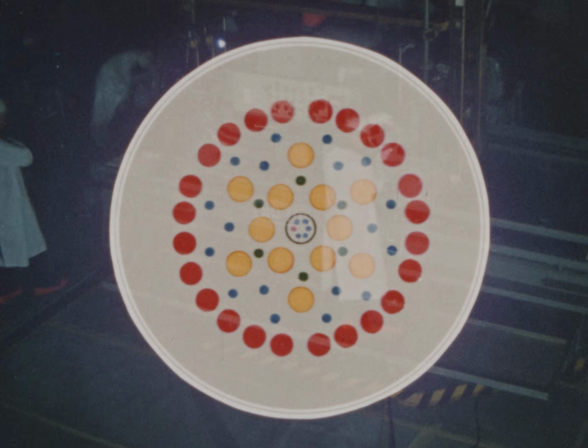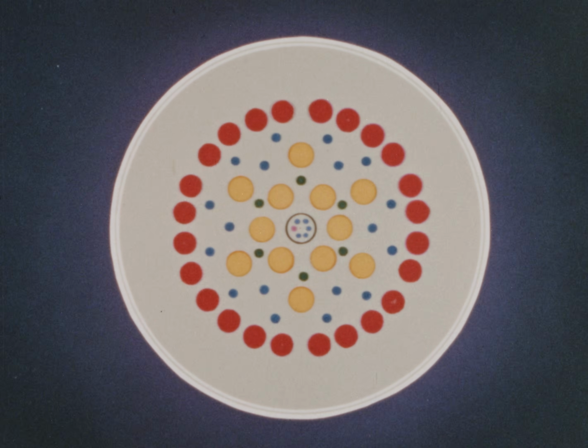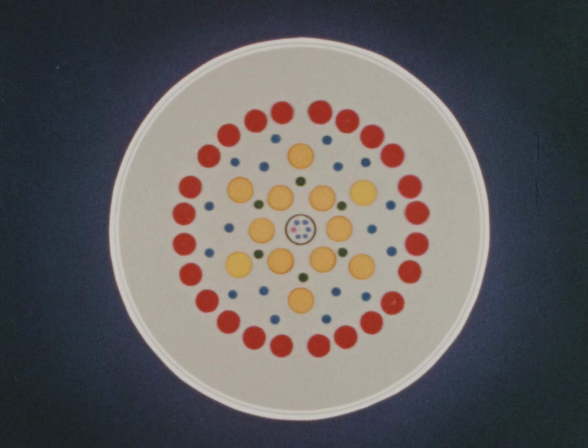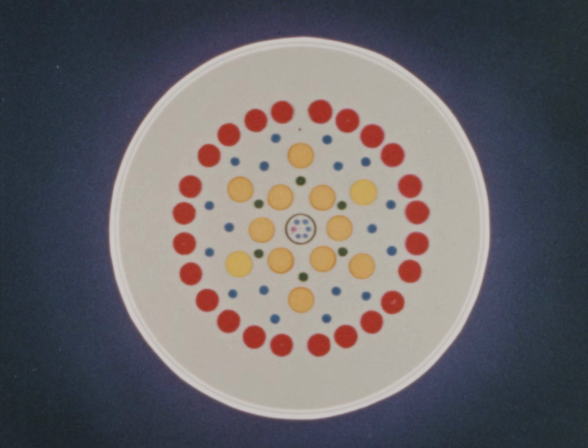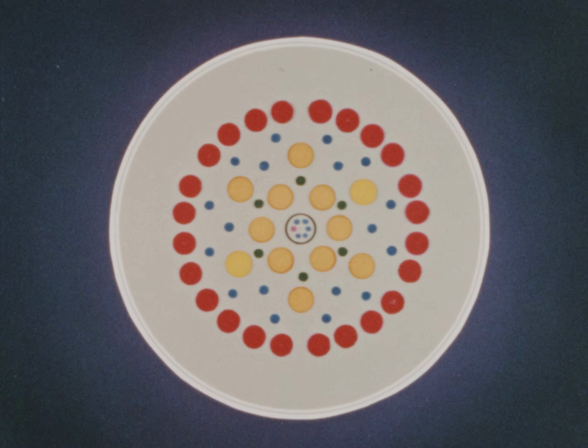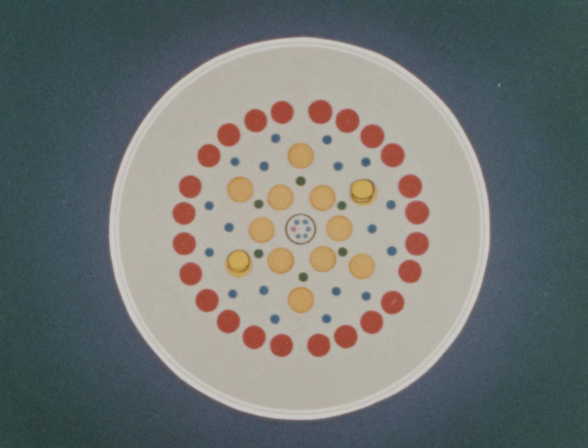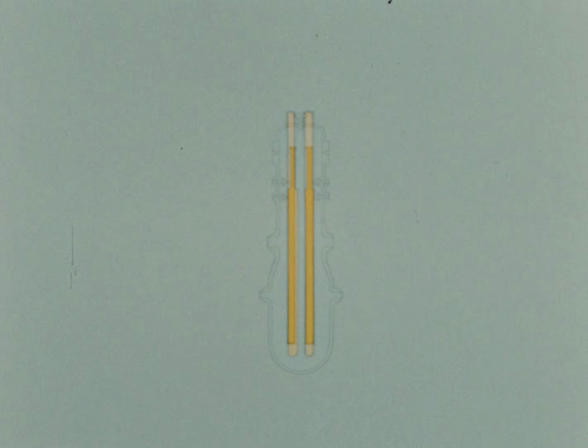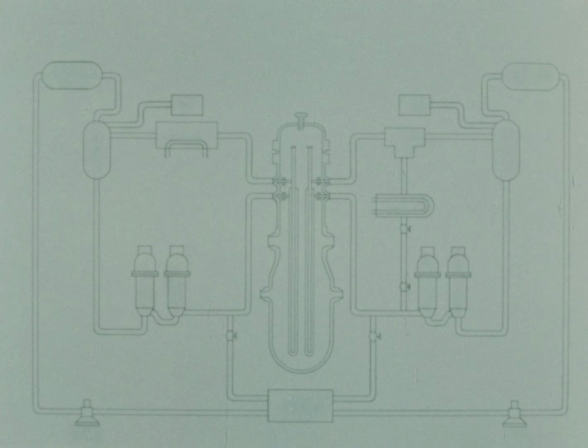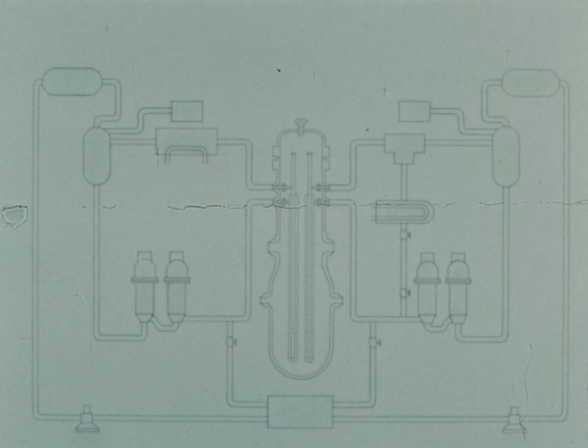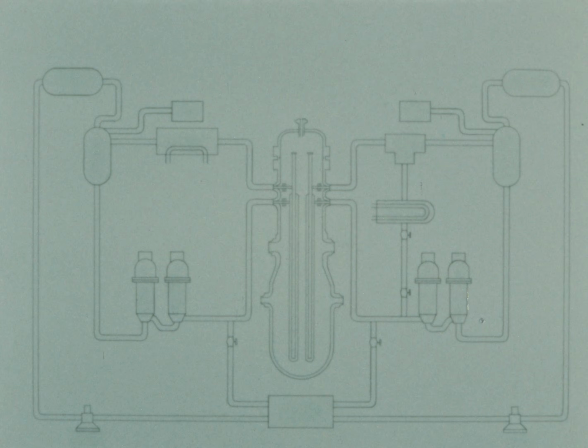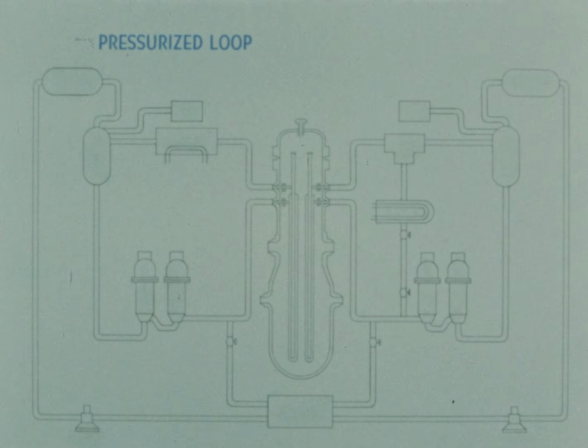In order to test fuel elements under a variety of physical conditions, the reactor vessel was designed with inlet and outlet ports to accommodate isolated coolant loops of the re-entrant type in the 6 outer test positions. 2 such loops, both fabricated of stainless steel, were installed during construction of the reactor. One can be cooled with liquid D2O at pressures up to 500 psi above the core pressure.